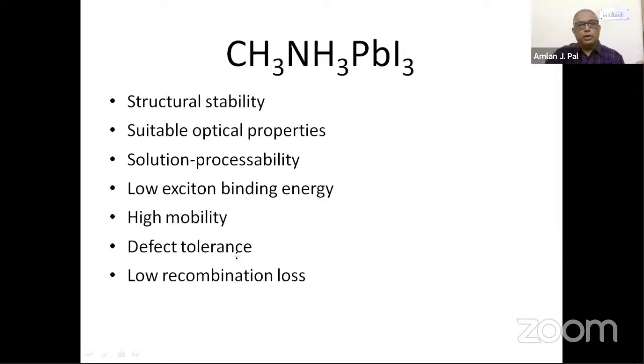And we also need defect tolerance, because these materials are being formed in the solution process. And of course, in the solution process, it's not a perfect single crystal. So there are a lot of defects. But thankfully, the energy of these defects is not disturbing the carrier transport. And finally, low recombination loss, because even if you separate the charge carriers, the most likely event is that they try to recombine and give you light or non-radiative recombination. So this recombination must be minimized, because unless you minimize the recombination, no device will succeed.